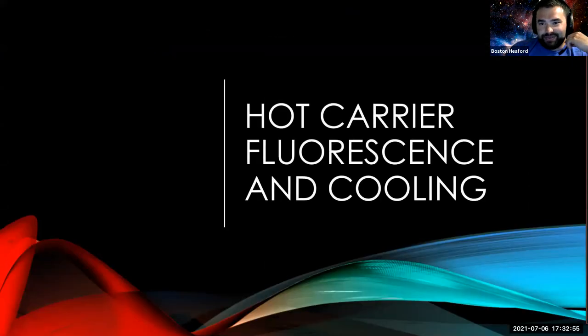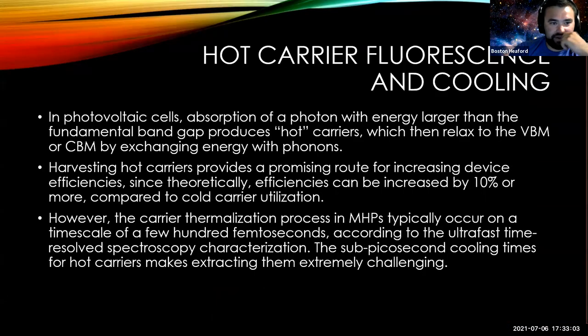And so that was it for the 2D perovskites, and on to the last section of hot carrier fluorescence and cooling. So in photovoltaic cells, the absorption of a photon with an energy larger than the band gap can produce hot carriers, which will then relax to the valence band maximum or the conduction band minimum by exchanging energy with phonons. Being able to harvest the hot carriers can drastically increase the efficiency of the solar cells as compared to just cold carriers.